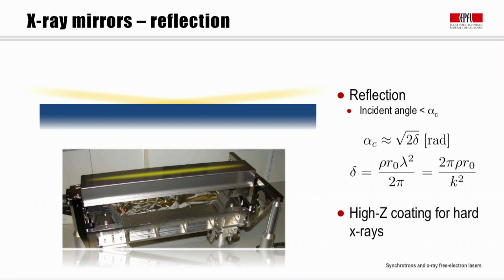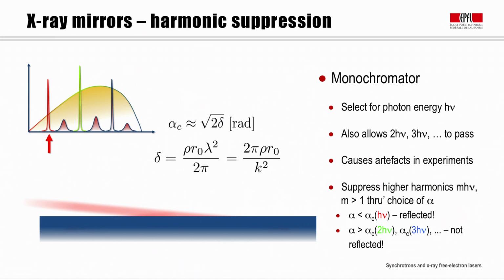Mirrors thus commonly have stripes of coatings of different densities, so by a simple lateral movement of them, one can switch from one material to another on the same mirror surface. So, for example, the uncoated part of a silicon mirror has a critical angle approximately 3 times smaller than that of the part coated with a platinum layer. This aspect of the energy dependence of the critical angle can be used to advantage.